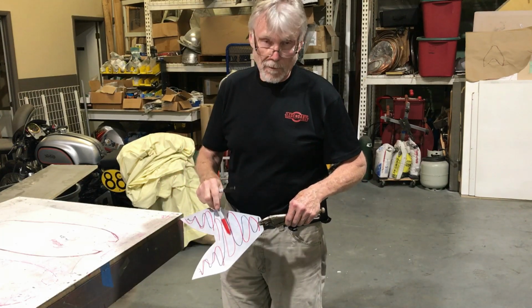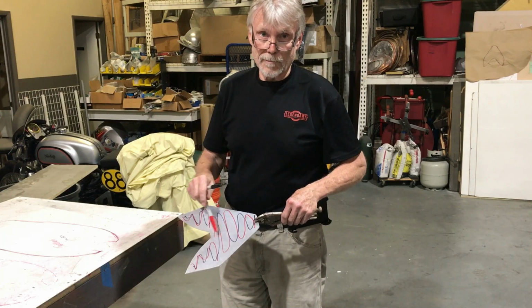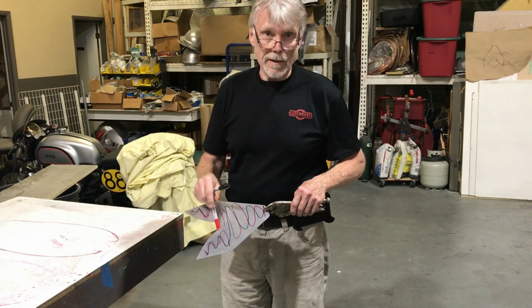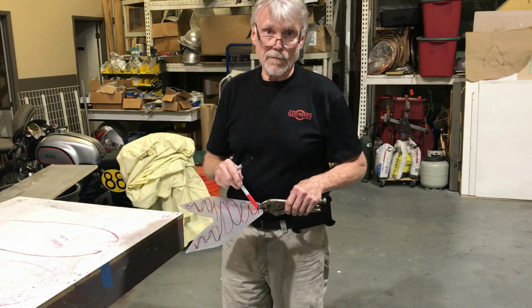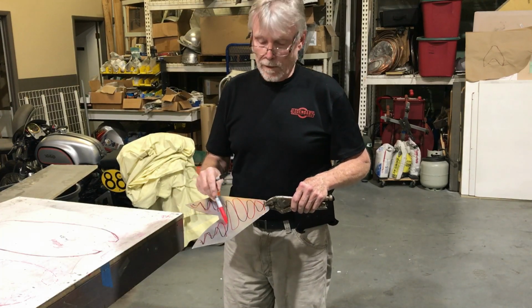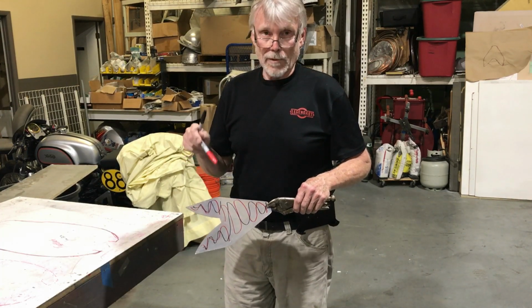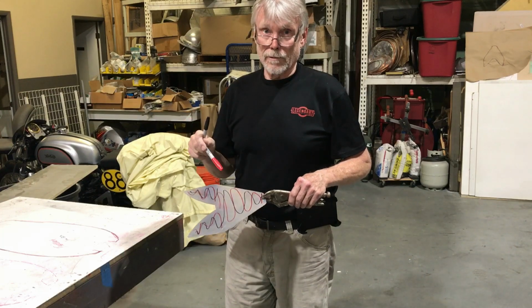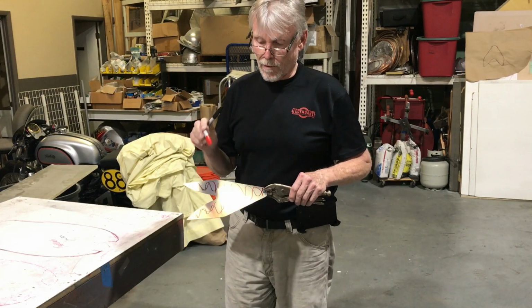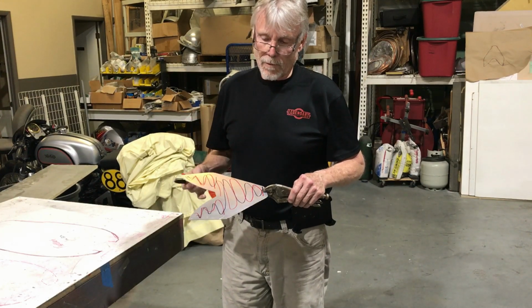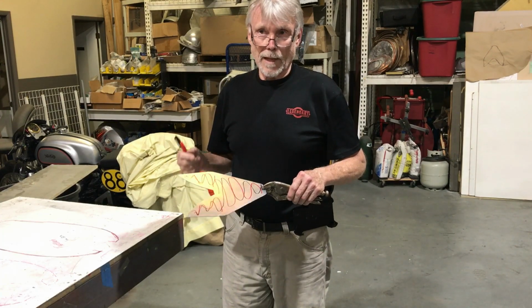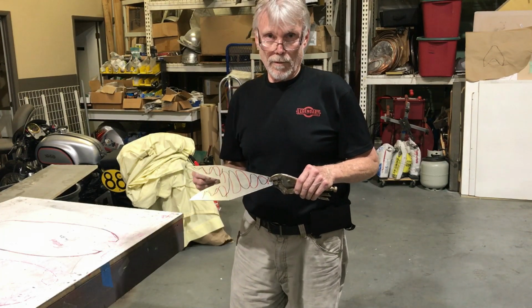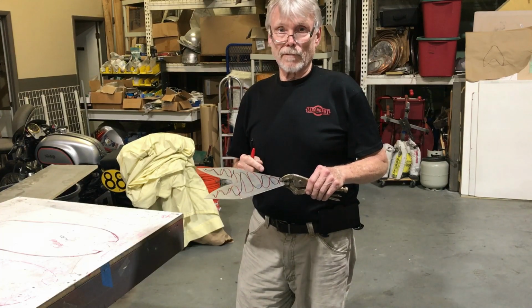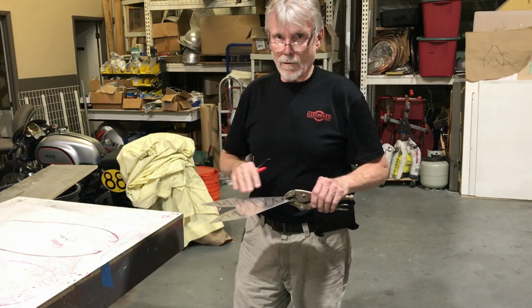And you want to be careful you don't burn the aluminum. If you see a big dull gray spot in it, that means you burned the aluminum. You've basically separated the structure between the aluminum molecules in here. You just don't want to do that. It makes it harder to work with, and there's a lot more chance of it breaking through when you're trying to shape the piece of aluminum. So you just want to make sure it's all uniform.